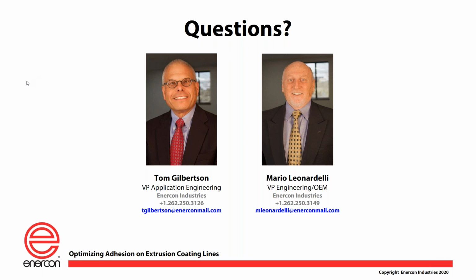Tom, this question could go in a couple different directions. Do we have a table comparing the analysis of a contact angle ink droplet versus the treatment dyne level measurement? We don't. Now, I will again give you a little historical reference here. Some years ago, we did a 24-month comparative test between a goniometer, this sort of grandfather device for measuring contact angle, with actual dyne testing. And we did the test comparing this droplet test of distilled water versus the solvent style dyne fluid, standard at the time. And while there were instances where we could get some comparative numbers, they were never consistent, and certainly not consistent between different film types.